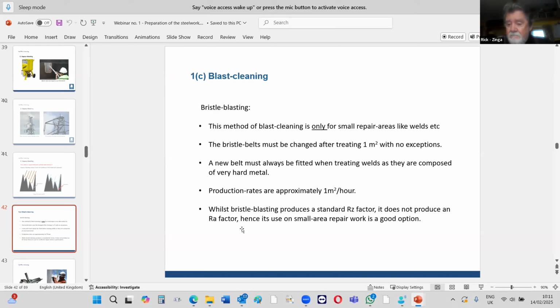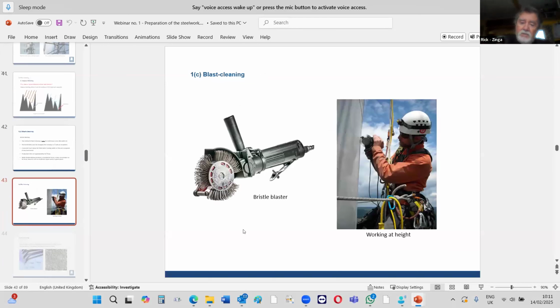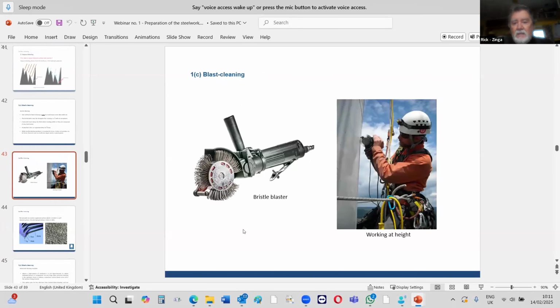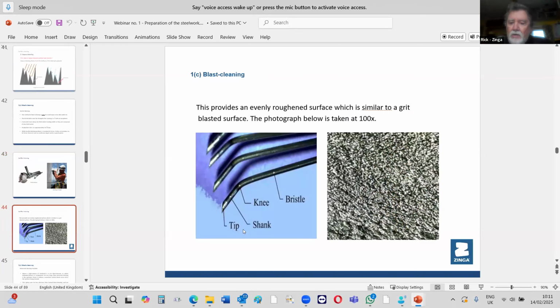Yeah, the belts. You have to replace the belt after 1 square meter. So if you're doing 10 square meters, that's 10 belts, and that's about 300 euros. So you'd rather get a guy in with a blaster and give it a quick sweep blast. Even that is still cheaper than bristle blasting, but it is for small areas and treating welds and critical areas. Very fast and fantastic. See, this is the guy doing a weld on the side of a turbine tower.